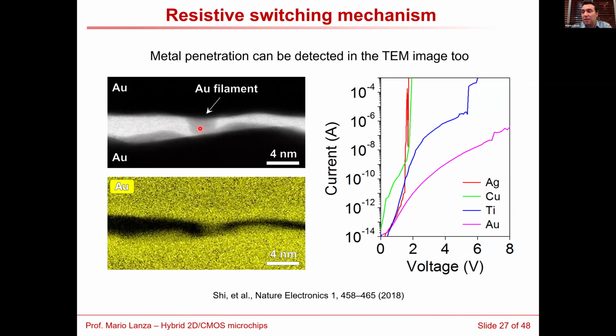We also fabricated devices with different top electrodes, applied an electrical field, and observed that the speed of breakdown depends on the diffusivity of the metal used. So basically, this is also one indication that what forms the filament is metal penetration into the boron nitride.